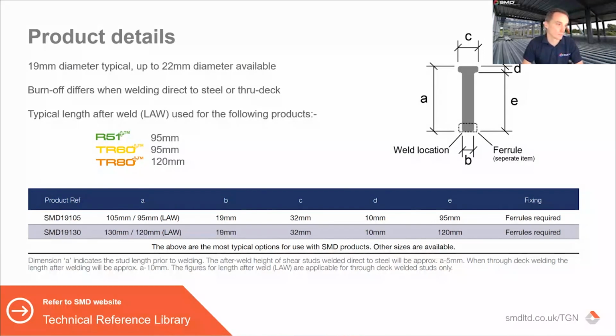Pre-weld, the stud will be longer than after weld, and the important thing to note is if you're welding direct to a beam, the burn off will be less than if you weld through the deck, purely because of the amount of protrusion that you need to burn through the deck and then into the beam.